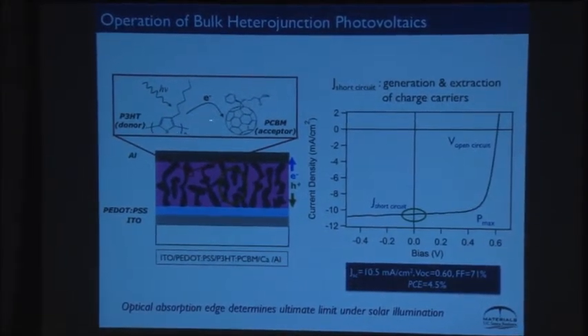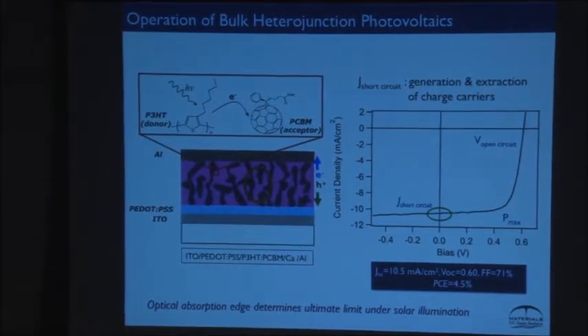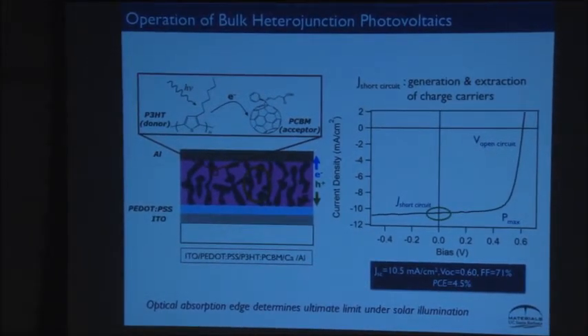The charge generation only happens at a molecular interface of these two, and that's very critical for the short circuit current. You want to absorb as much light as possible and extract the charges out to the electrodes. With a particular incident amount of radiation, the short circuit current is set by how many of those absorbed photons can be converted into electrons and holes and then pulled to the electrodes. That critically depends on the interface area of the two materials, since the only time you get charge is when those two things meet.